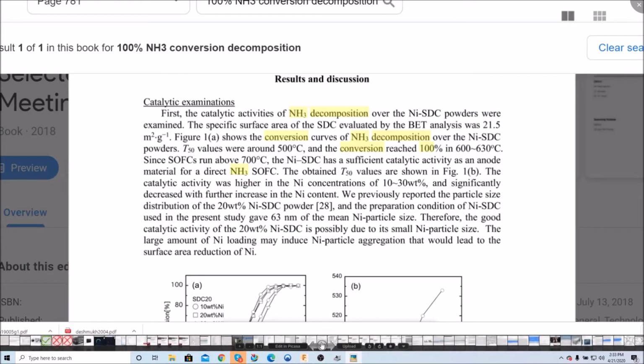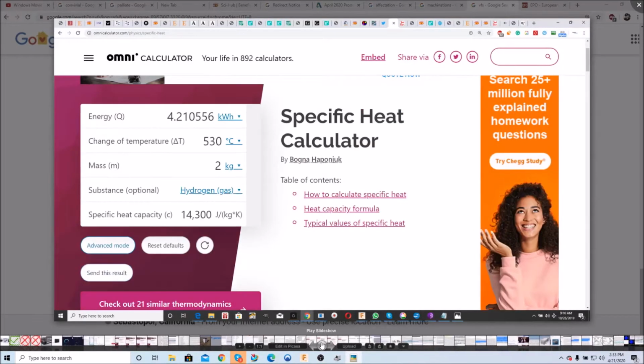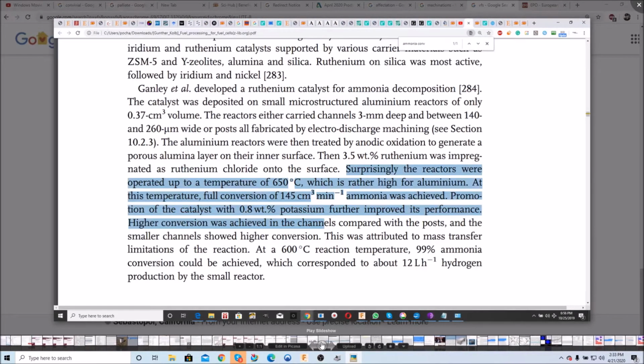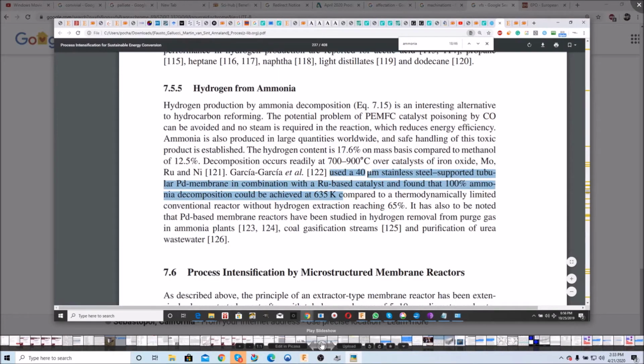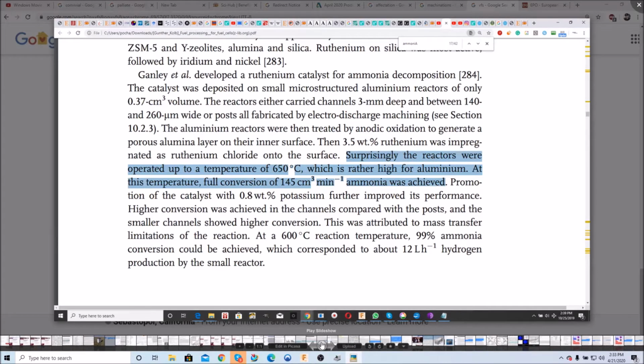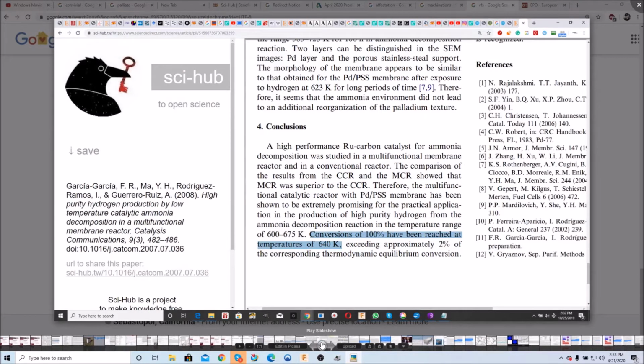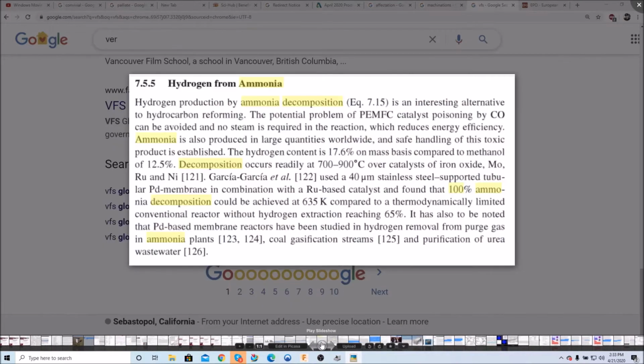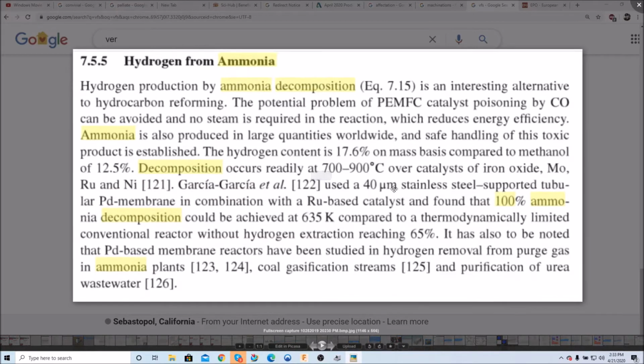So just more data on catalysts. We're going to go over the ruthenium catalysts pretty soon here. And people have studied all sorts of catalysts. There's one sodium amide catalyst that was studied. Just again, a plethora of catalysts that have been investigated. None of them perform very well except for ruthenium. So here it was found that ammonia achieved 100% decomposition at 635 Kelvin.